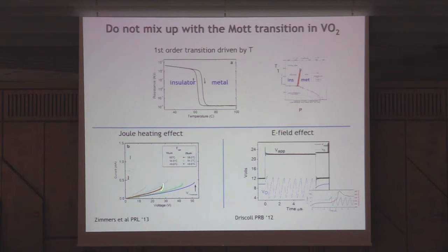In any case, I think I'm quite in agreement with what Ivan told us about, but I want to emphasize here that we're going to be considering an insulator which is there. So by applying an electric field to that, we can only move here. So at higher temperature, by heating, you're never going to get to a metal. So here, you heat, you have a transition, a dramatic transition to a metal. Here, there is no dramatic transition to a metal. And if you cool, you would go to another insulator. So that's not the same situation here.